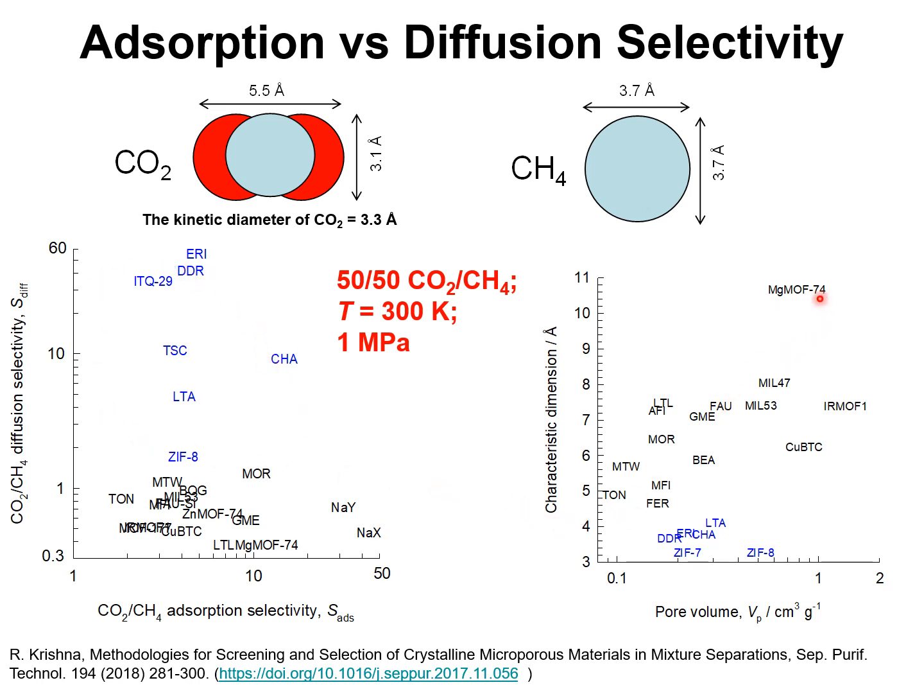The other structures indicated in black, such as magnesium MOF-74, have significantly larger channel dimensions, typically larger than about 5 angstrom. For example, MFI zeolite has channel dimensions of 5.5 angstroms. IRMOF-1 has characteristic dimensions of about 9 to 10 angstroms. MIL-47 is about 8.5 angstrom channel dimension. Faujasite zeolites typically have a window size of 7.2 angstrom. Magnesium MOF-74 consists of hexagonal channels of 11 angstroms.